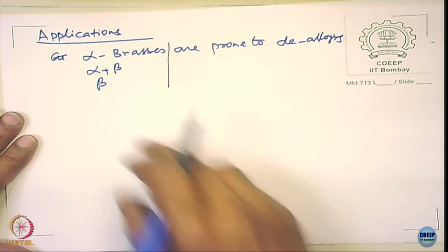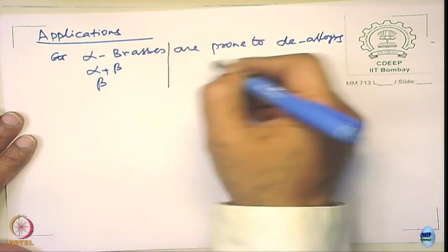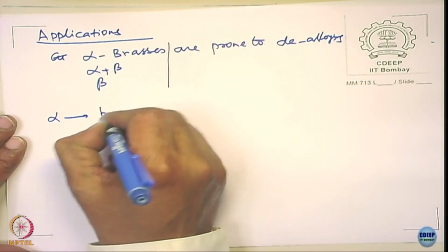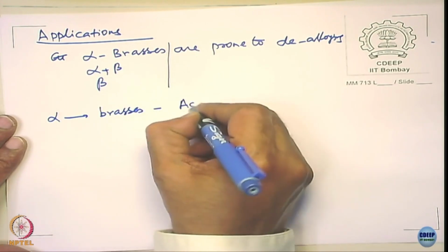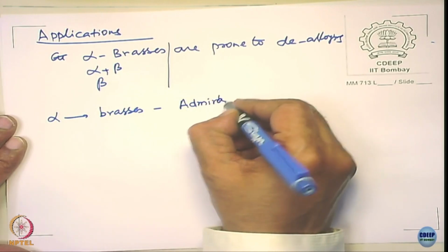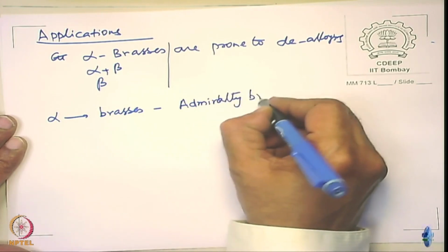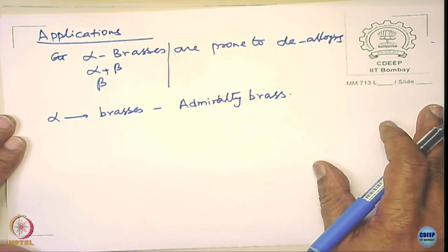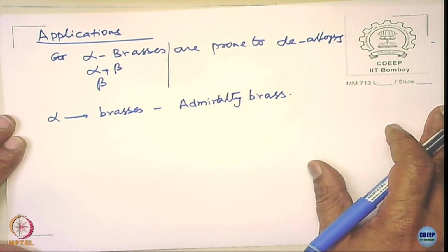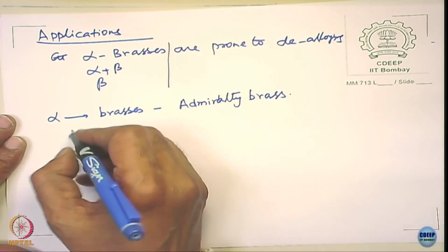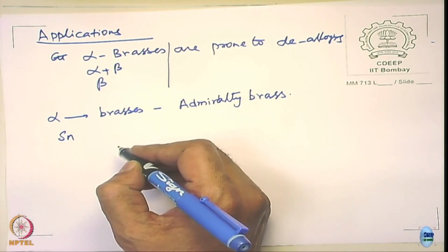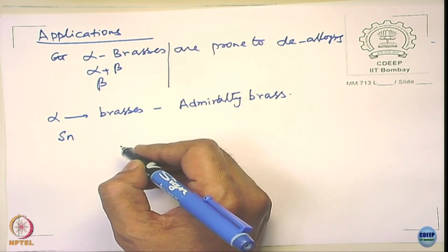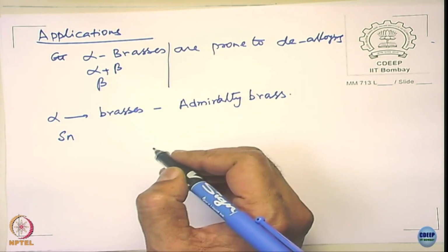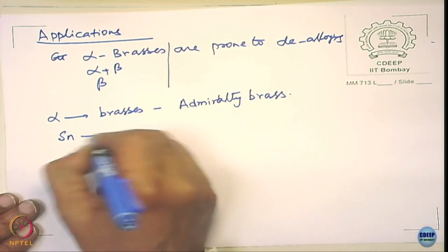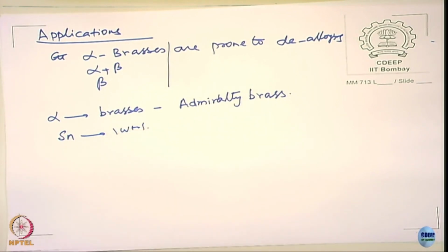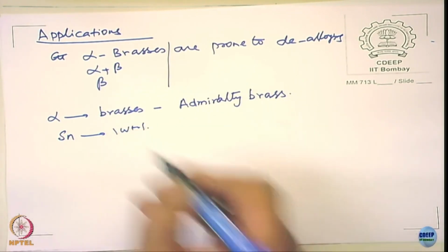What people have done actually in order to avoid this disintegration process in alpha brasses, you might be knowing what is called Admiralty brass, right. I think people from the Navy know it; it is Admiral who first formulated this particular alloy actually. So, that is why it is called Admiralty brass. The Admiralty brass consists of tin, it is about 1 weight%. So, about 1 weight% of tin is added to alpha brasses.